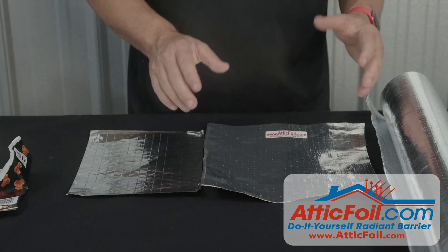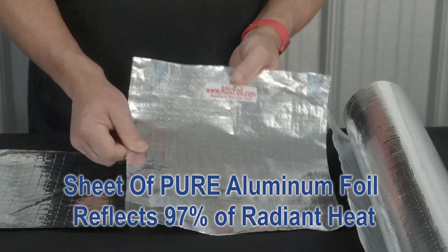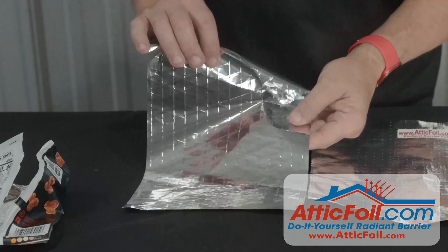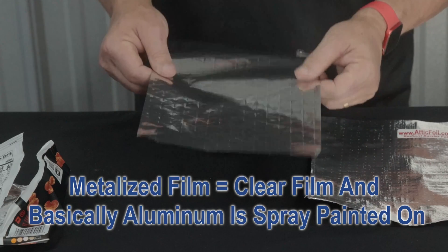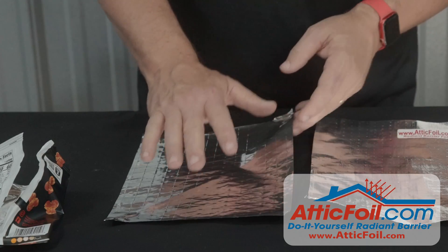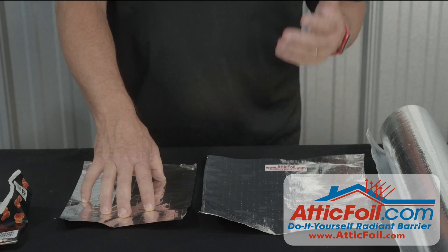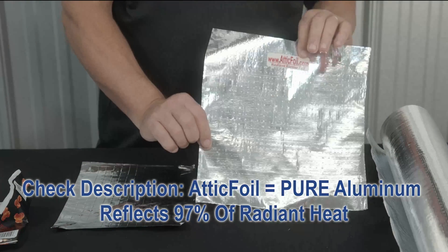The first part is how they're made. Attic Foil uses a sheet of pure aluminum foil — this is actually like kitchen foil — that's laminated onto a heavy tear-proof tarp-type material. Whereas most of the competing products that are less expensive use what's called mylar, or metalized film, or MPET. This is basically a clear piece of film that has a vapor-applied aluminum. The actual layer of aluminum is one two-hundredth as thick as the aluminum on the Attic Foil. And the way you can tell the difference in the description is the Attic Foil will reflect 97% of the radiant heat.